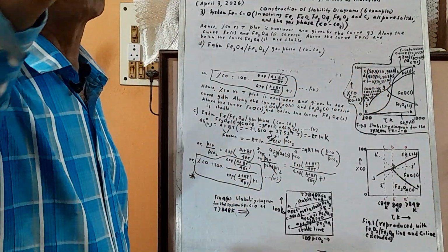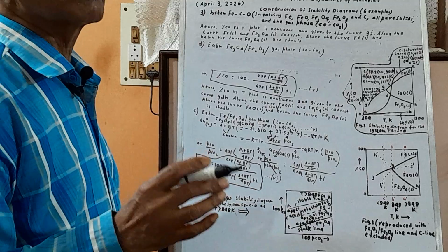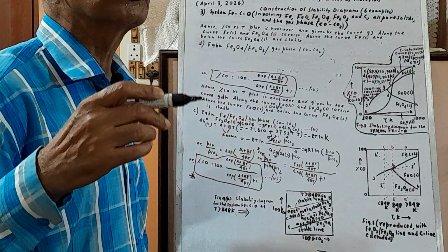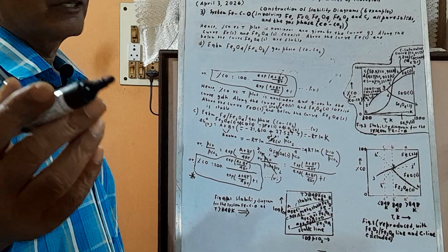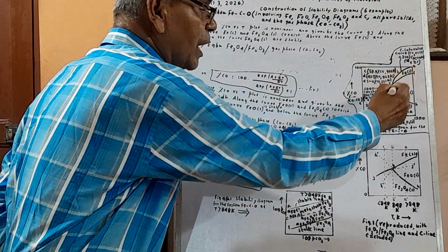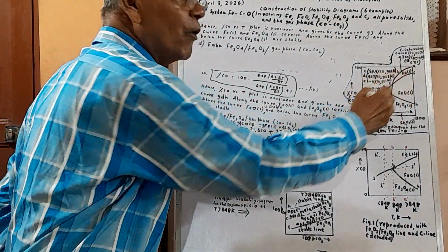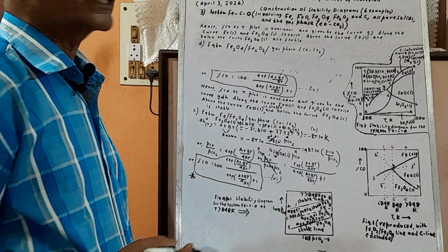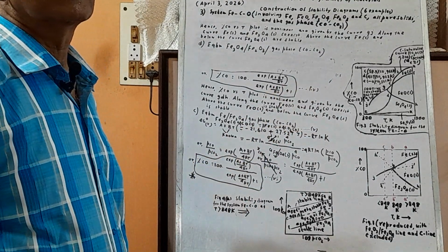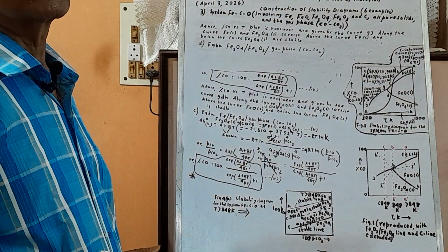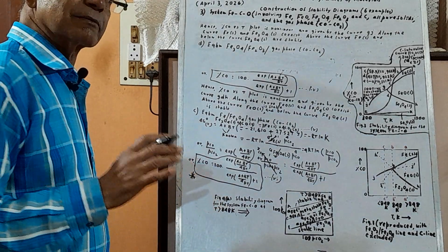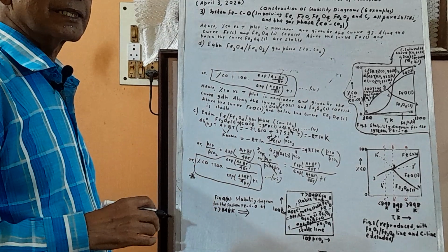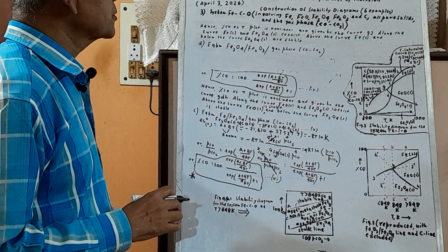If nitrogen is 50%, say, then the total pressure constituted by CO2 is 0.5. So you have to draw a new curve corresponding to 0.5 atmosphere, and then you apply it. And you know the percentage of CO and CO2, the gas composition. So there are intricacies, but you have to be smart also.